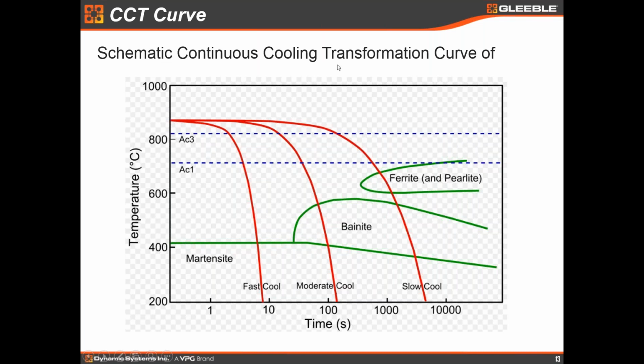So this is simply a curve that shows some maps of different structures that can be formed on cooling of a steel and cooling rates, faster, moderate, and slow cool. And if you superimpose those cooling rates over this, I'll call it a structure map, you can predict based on the experiments that have been done using dilatometry, what phases you're going to get.